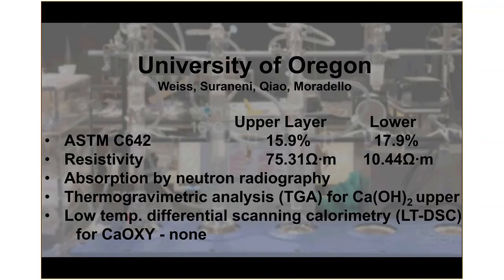The thermal gravimetric analysis, TGA, again, going to be very different because there's going to be calcium hydroxide in the upper concrete, and there's none of that left in the lower concrete because it's fully carbonated. Low temperature differential scanning calorimetry, another very interesting test that Jason Weiss is experimenting with. In this case, he was looking for calcium oxychloride, which is a destructive, kind of a ghost mineral, but a very destructive ghost mineral. And he found none of that. So that's kind of wrapping it up with those analyses. I'm open for questions, I believe.